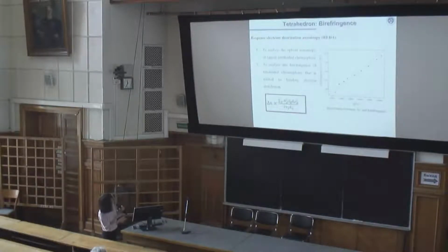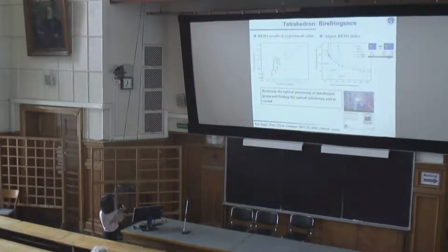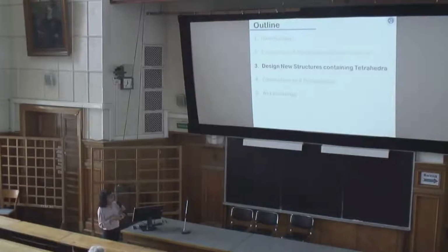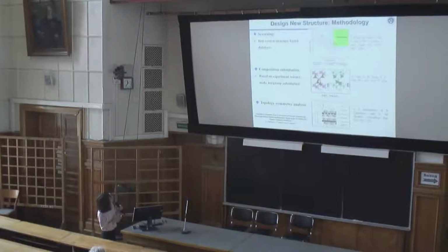Also here, we checked the birefringence against this key factor, and they are proportional to each other. The calculated birefringence and the experimental one are consistent with each other. So we can adjust this important factor to enhance the birefringence. And based on the mechanism, we try to design new structures which only contain the tetrahedral group. Firstly, scientists usually have several methods for this. One is scanning the existing structures from a database, and then they calculate and tell the experiment which one is good and which one is not good.